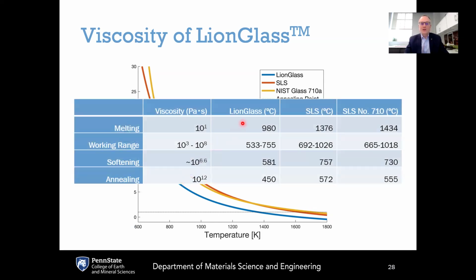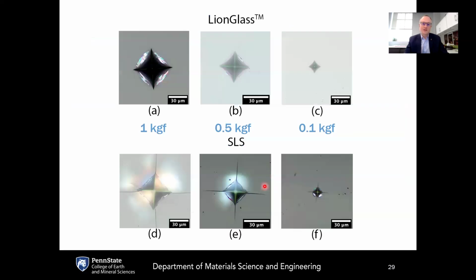And you can compare isokom temperatures here. So melting, the same temperature that's around 1400 for soda lime is like 980 degrees C for LionGlass. Working points get shifted down, softening points get shifted down, and the annealing temperature of LionGlass gets shifted down, although not by as much. It anneals at about 450 degrees Celsius.